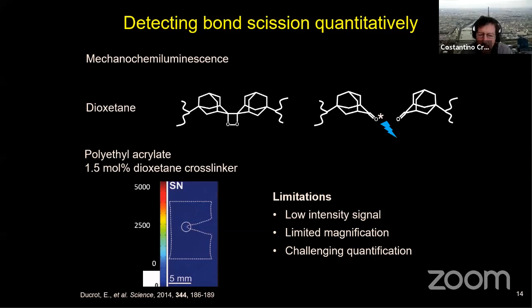The problem, though, is that the signal is relatively weak. You really need a sensitive camera to do the measurement, which means that you tend to lose resolution because the noise becomes important, and the magnification cannot be very high. Plus, if you can only do dynamic tests, quantification, or for example, using confocal microscopy for 3D images, is not really possible. So there are a number of limitations. The synthesis is also maybe trickier, even compared to other organic chemistry molecules. So we were very keen on trying the fluorescent one.